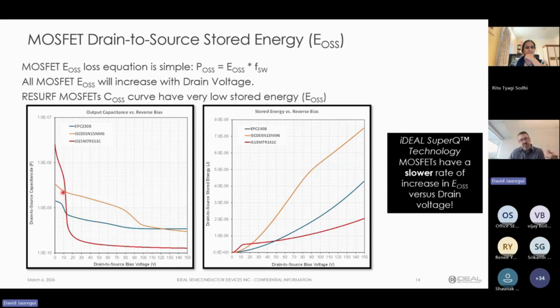Here's the same Infineon OptiMOS 6, similar RDS(on). They start midway, and they come down, and they actually end up lower than the third curve, which is an EPC device. Starts low, has that change. You can see, like I said, all technologies have some change of capacitance, and then it flattens out. So what does that mean, right? Is this a good thing or a bad thing?